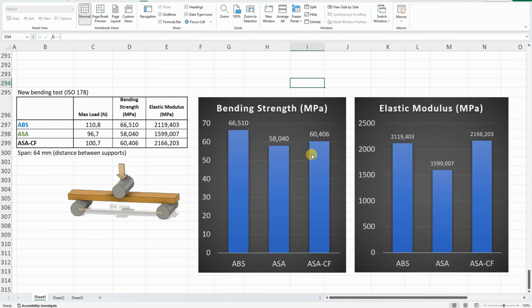Here I expected a bigger value. Elastic modulus shows how stiff is the material because it depends on the deformation too. And here just a little bit small advantage on the ASA-CF side compared to the ABS. And of course the weakest is the ASA.